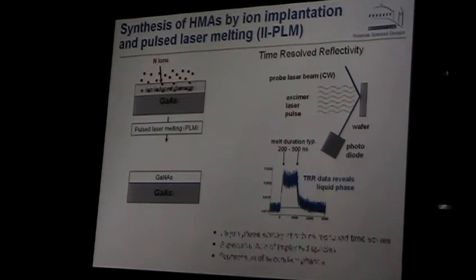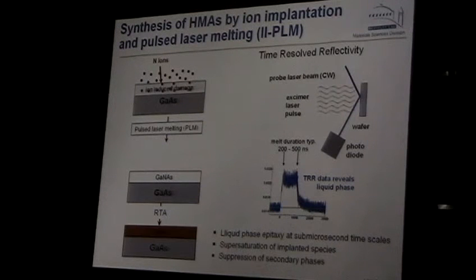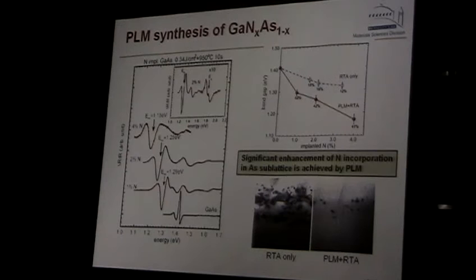Everything is cold. Gallium arsenide is cold, but if you melt it, then of course it regrows very rapidly. The times are some microseconds, and you can test it with reflection study how it changes. So we have eventually material which has nitrogen trapped in. The nitrogen cannot escape, and sometimes we anneal it even further, a little bit, not to high temperature. So we can get a good material, in fact, in this case.